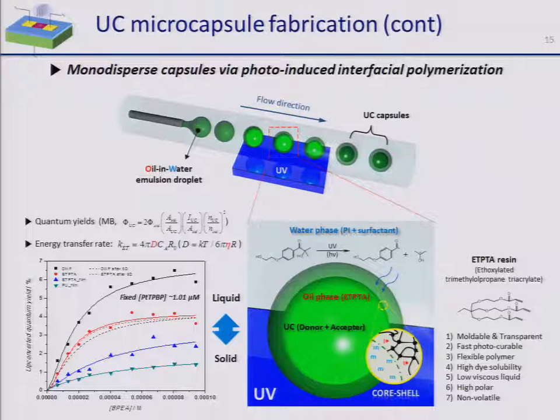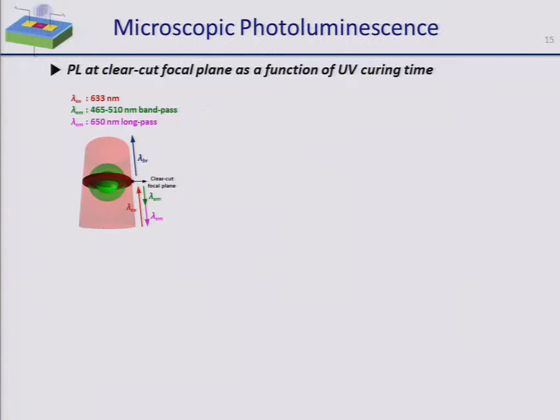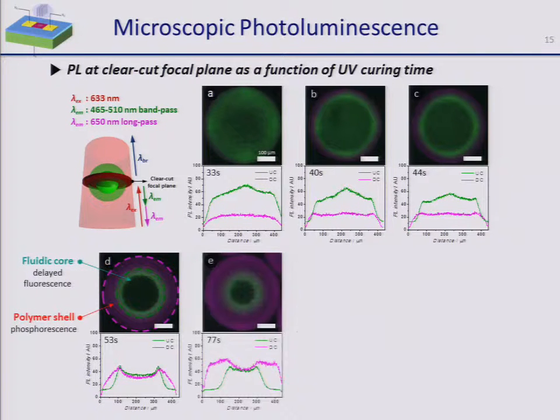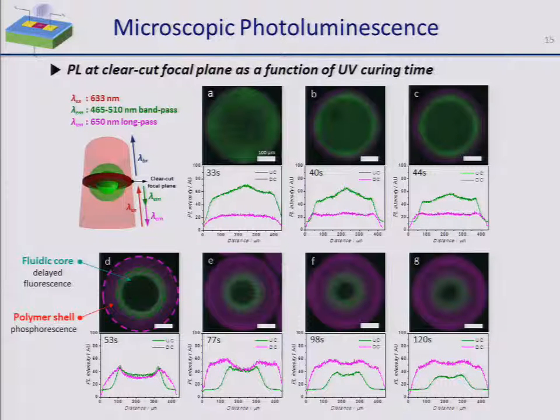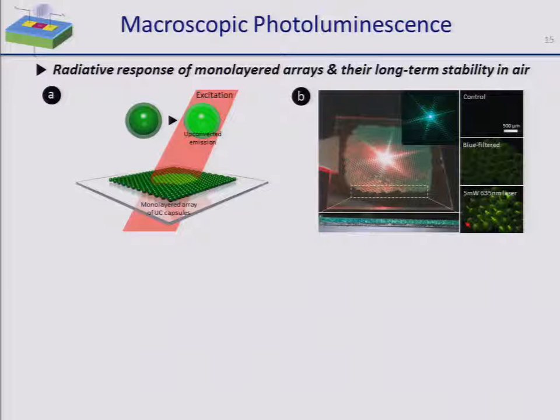And depending on the concentration and the time of polymerization, we can get control of the thickness of the shell, and we can have anything from a very thin shell and a floppy microcapsule to something which is basically solidified. Right, so if we look at photoluminescence, cutting basically through the center of those microcapsules, we can see that as a function of curing time, we can increase the thickness of the shell, and you can see the profile. And if we take an array of these microcapsules and irradiate them, we can see emission of the microcapsules at a shorter wavelength.